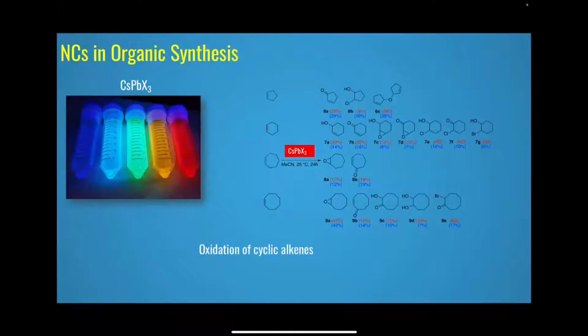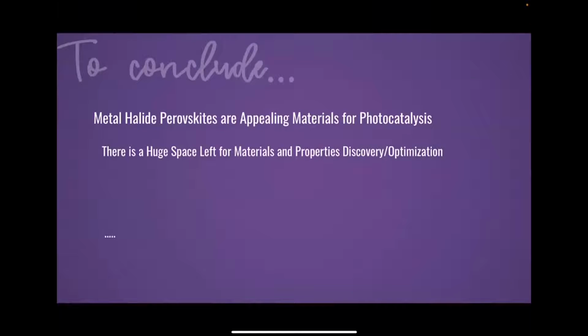And finally, we are also exploring the use of nanocrystalline metal perovskites. You see the series of cesium lead tribromide. Here we still keep lead. This is the only case where we keep lead, because it's nearly impossible to get highly active nanocrystals based on tin. You see here the fluorescence of these nanocrystals, and we are using them in several kinds of organic reactions, for example, oxidation of cyclic alkenes or acyclic alkenes, and many other organic reactions.